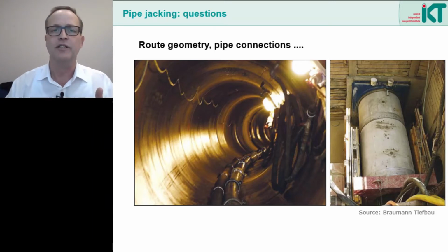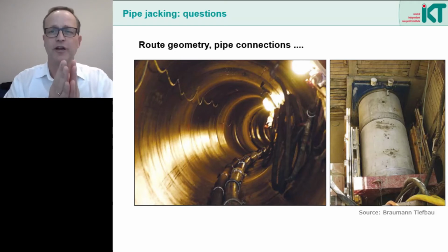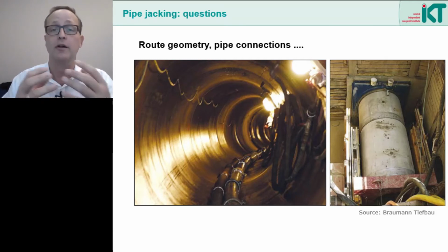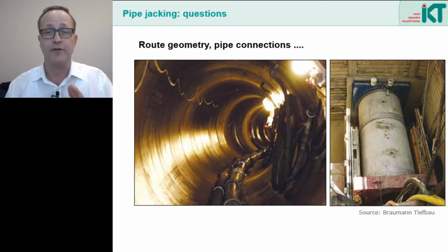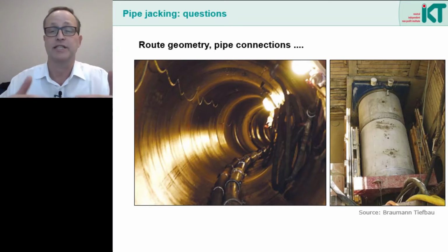However, this also means that in a curve the pressure transmission ring is very strongly compressed on one side. And at these points the stresses in the reinforced concrete are also very high. Any miscalculation or steering error can then lead to damage, such as spalling of the concrete.